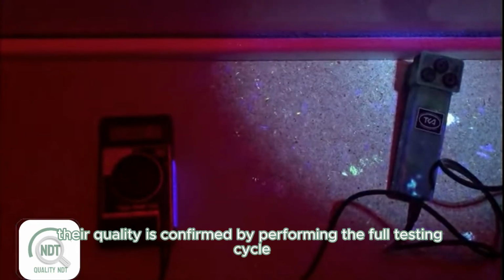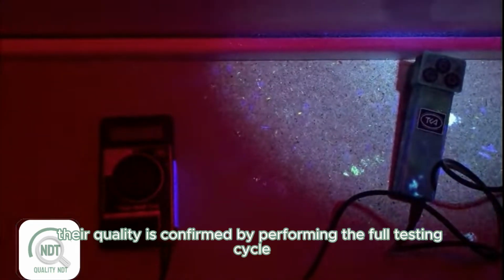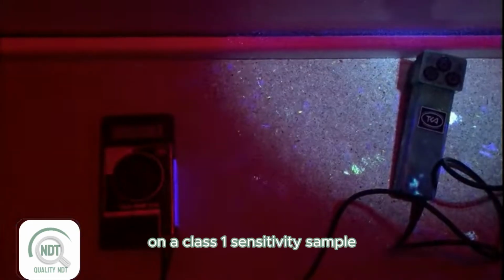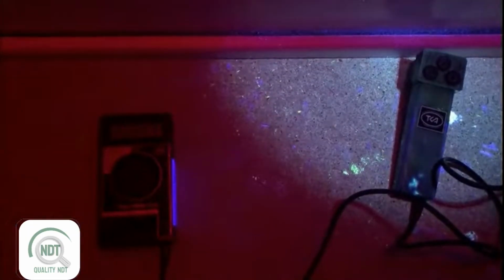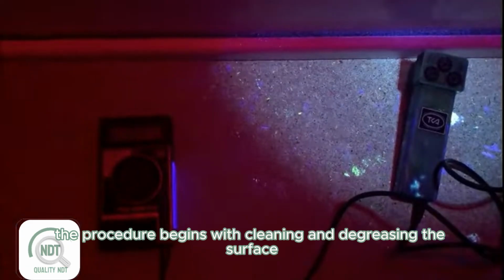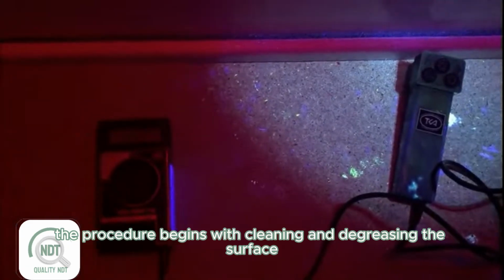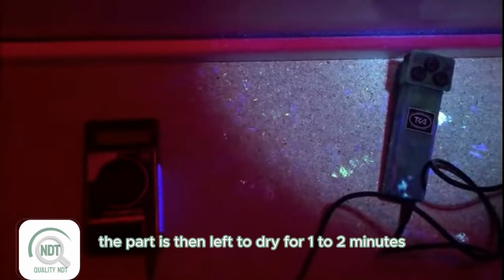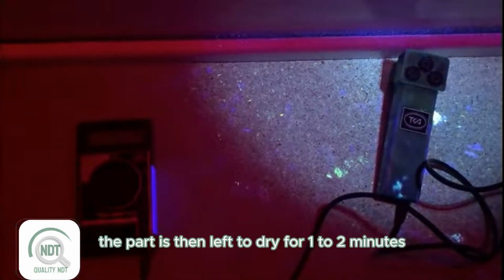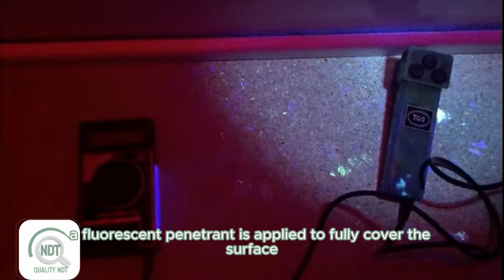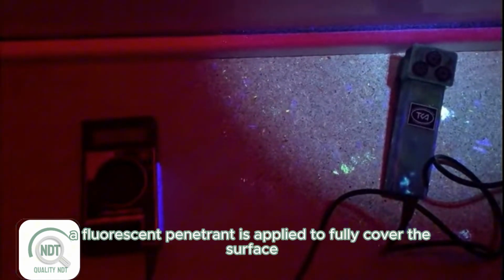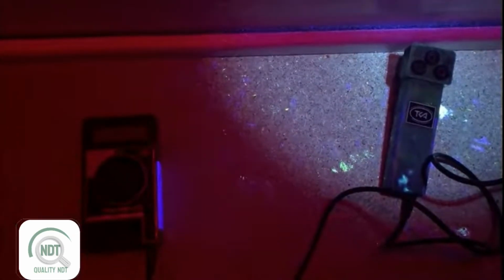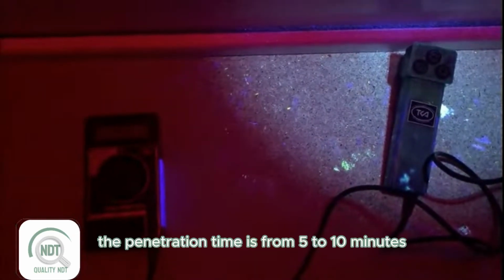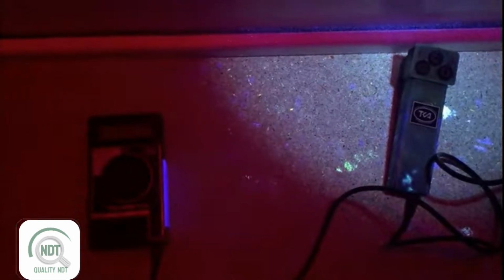Their quality is confirmed by performing the full testing cycle on a Class 1 sensitivity sample. The procedure begins with cleaning and degreasing the surface. The part is then left to dry for 1 to 2 minutes. A fluorescent penetrant is applied to fully cover the surface. The penetration time is from 5 to 10 minutes.